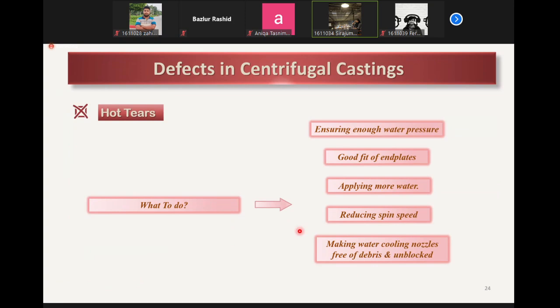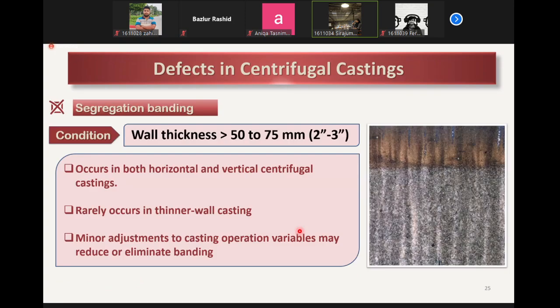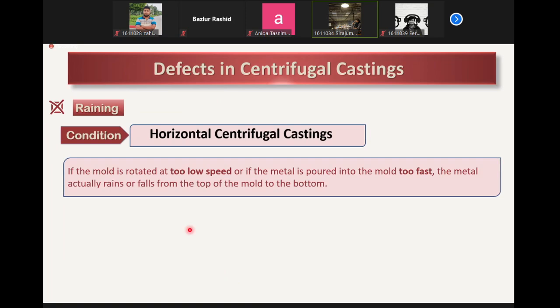Another type of defect is segregation banding, which occurs only in true centrifugal casting. Generally, it occurs where the casting wall thickness exceeds 50 to 75 millimeters; it rarely occurs in thinner wall casting. Minor adjustments to casting operation variables like rotational speed, pouring rate, and metal and mold temperatures will usually reduce or eliminate banding.